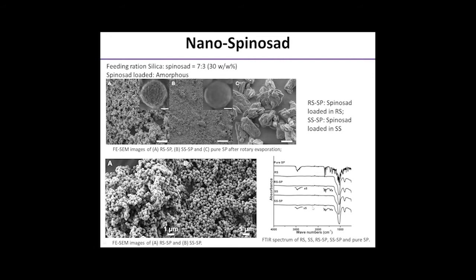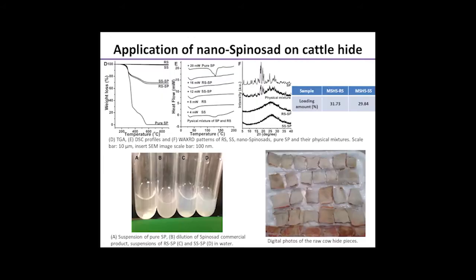The Fourier transform infrared spectra are also used to confirm the successful loading of spinosad, as the characteristic peaks of the spinosad can also be observed in the spectra of the two nanospinosad. The spinosad loading amount in the nanospinosad formulations was determined by thermogravimetric analysis, shown over here. Pure spinosad exhibits almost 100% weight loss at around 570 degrees C, while both silica nanocarriers show negligible weight loss. Accordingly, using this data, we can calculate the actual spinosad loading content in both nanospinosad, which is 30%, agreeing with the initial feeding ratio.